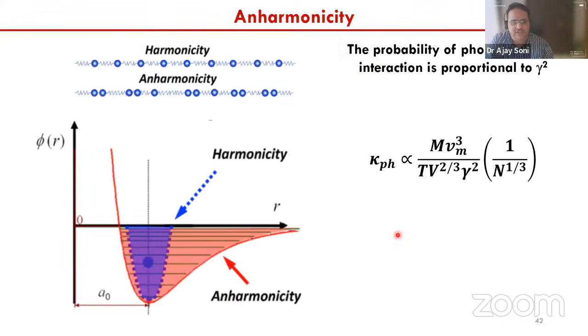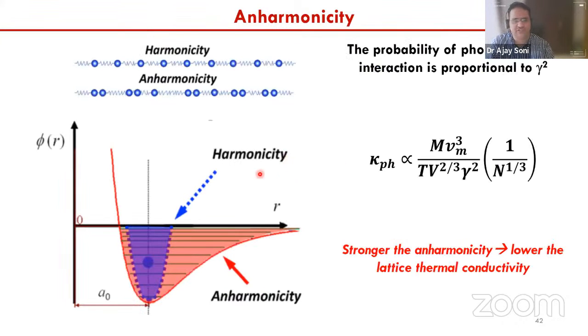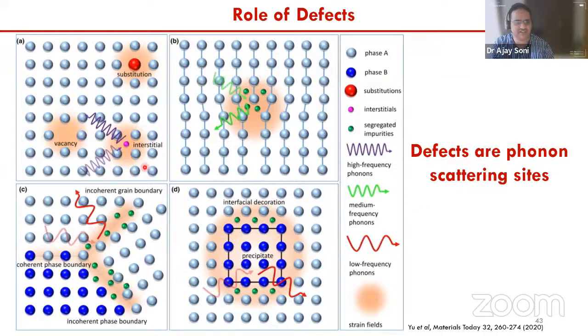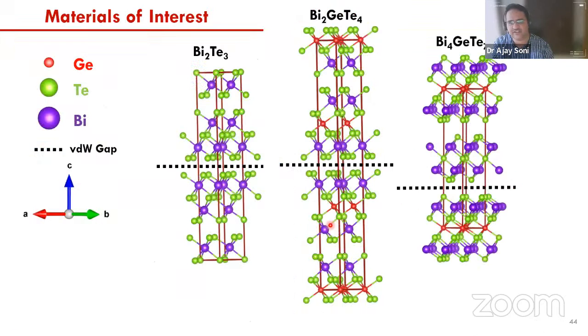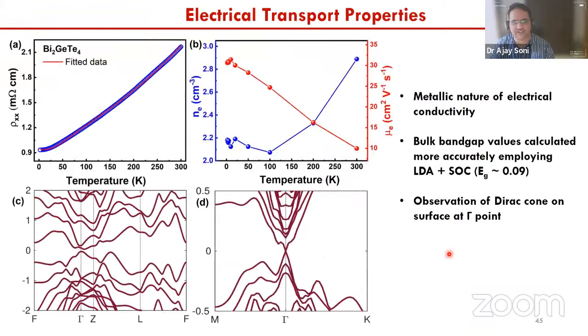And so what we do is one can create anharmonicity in the materials, which can affect the phonon thermal conductivity through the elastic properties, which depend on the Grüneisen parameter of the materials. So by creating different kinds of defects, you can engineer the materials. Recently we worked on bismuth telluride and germanium doped bismuth telluride based materials, where when you make these materials, they have different kinds of structures which are interesting for thermoelectric research. And these materials are also among the best quantum materials to study topological insulating properties. So you can see this from the band structure here.